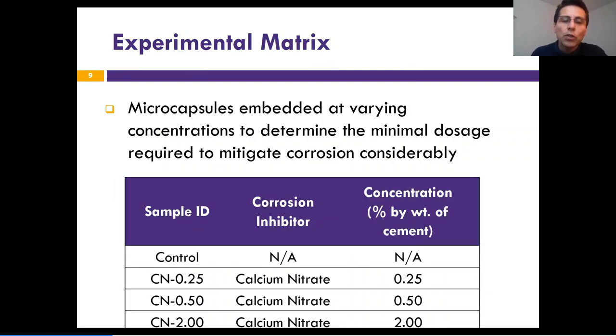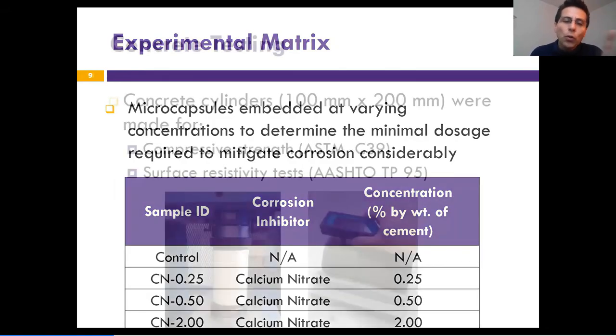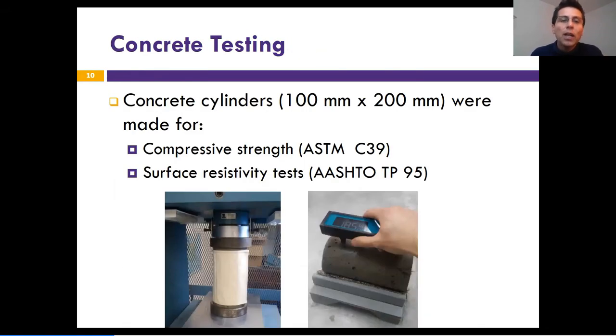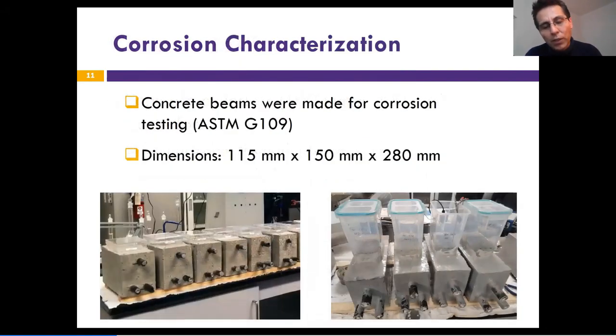So what we start to do is to have different concentrations of calcium nitrate. Based on this, we test each one of the microcapsules at each concentration. We also looked at the properties of the concrete based on the addition of these microcapsules. So we did the compressive strength and the surface resistivity tests based on these standards, as you are seeing, the ASTM standards.